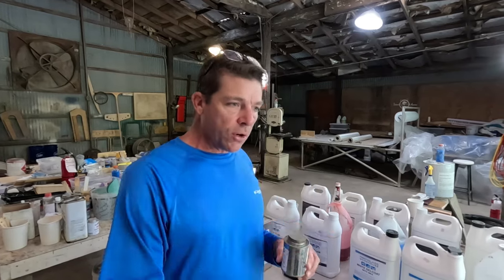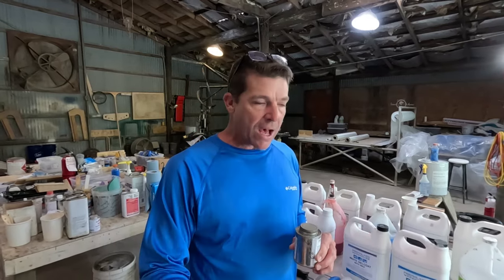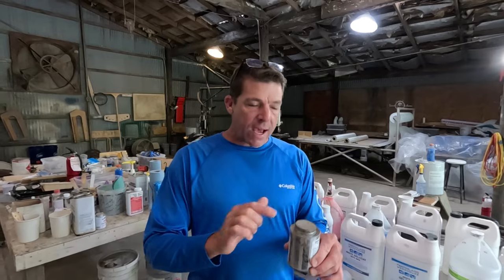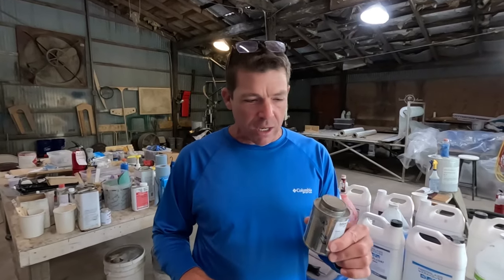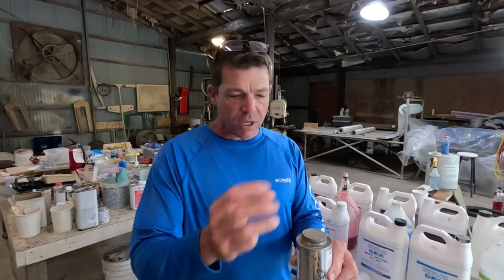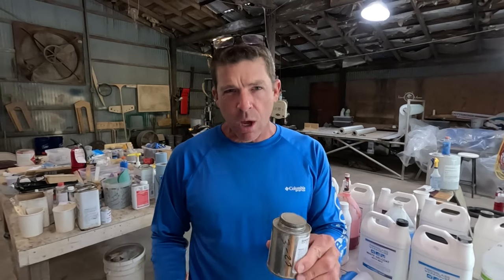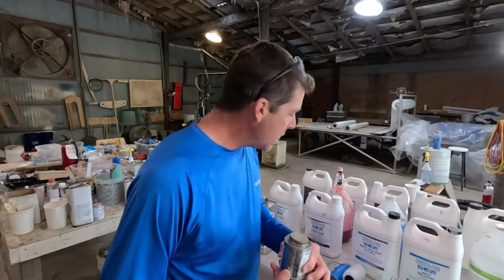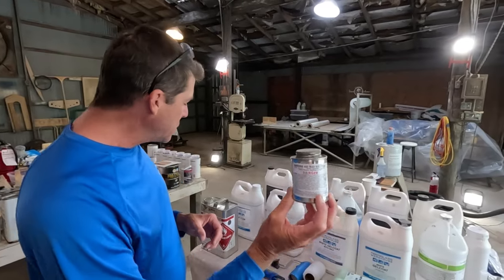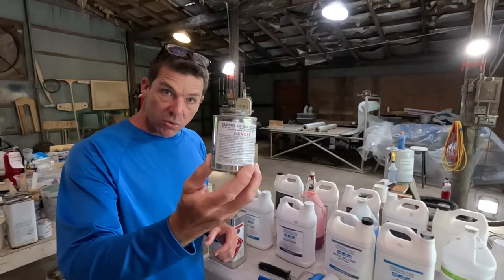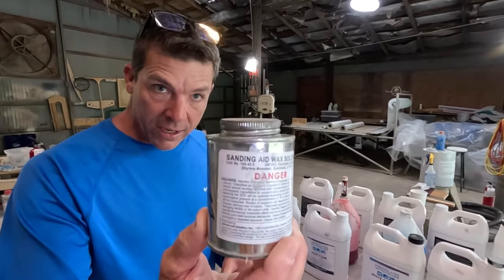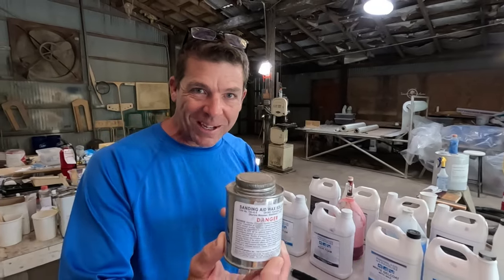say if you were doing three coats of interior gel coat like we did on our little skiff that we did the interior in a light gray, you would do the first coats without wax, and then you add, I usually go a little heavy, about a 3% solution. So pretty good capful of this, sometimes even two capfuls per quart of gel coat is gonna be the solution there. So that is the answer to the difference between wax and no wax. Wax on the last coat only, guys.